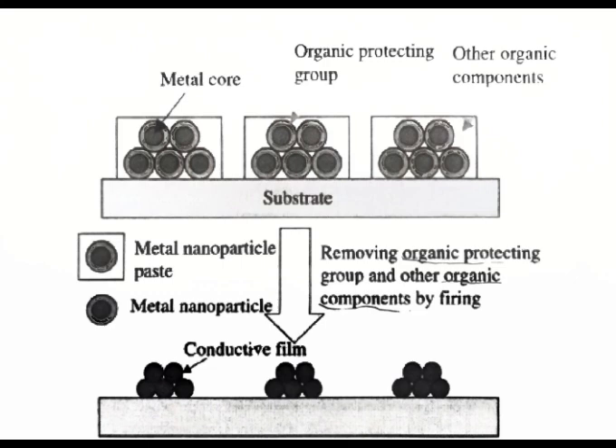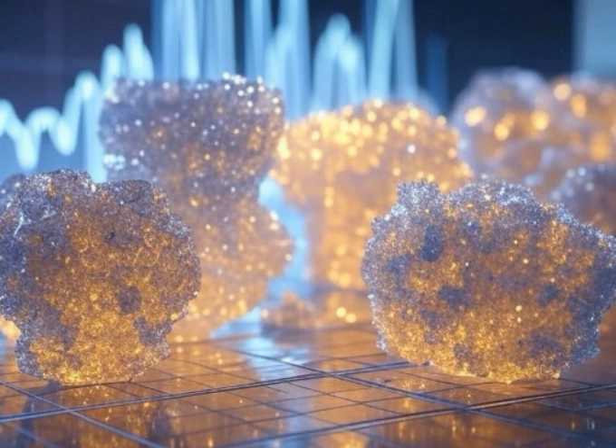Absolutely. So it greatly expands your range of materials and opens up these whole new design possibilities for flexible, even stretchable electronic devices. Right. And also because the nanoparticles are so small, you can achieve much finer circuit patterns. The presentation mentions being able to get lines and spaces less than 50 micrometers using screen printing. Wow. Which is a big jump in resolution compared to what you could achieve with those traditional pastes. And they're anticipating even being able to get down to 10 micrometer lines. Right. I mean, that's just amazing, the level of miniaturization.